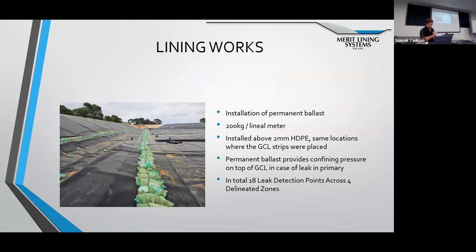Lastly, we installed permanent ballast at 200 kilograms a linear meter. This ballast was installed directly above the GCL to provide a confining pressure. Should ever there be a leak, that means the GCL can swell in that area and will allow the leak to be delineated to the different zones. In total, there was 18 leak detection points across the 4 zones.